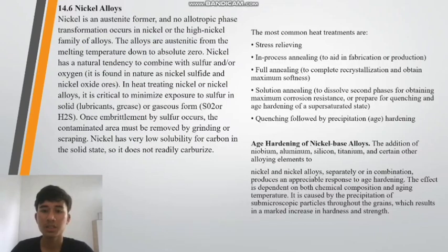In heat treating nickel or nickel alloys, it is critical to minimize exposure to sulfur in solid lubricants, grease, or gases such as SO2 or H2S. Once embrittlement by sulfur occurs, the contaminated area must be removed by grinding or scraping. Nickel has a very low solubility for carbon in the solid state, so it does not readily carburize.